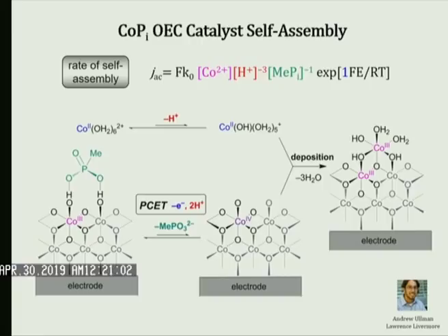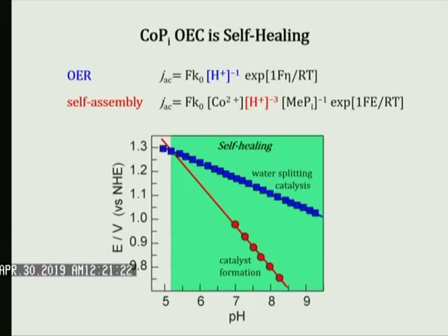So before I said you take cobalt-2 to 3, it lays down on the electrode, but it's through this complicated reaction sequence. And the thing about this sequence is that red term, it's inversely dependent on 3 protons. Now, why did we spend 4 or 5 years figuring all this out? Because this allowed us to make the first self-healing catalyst.